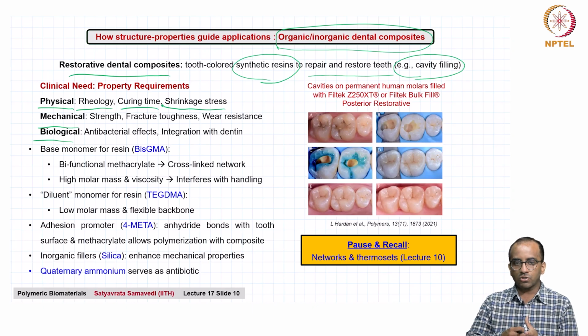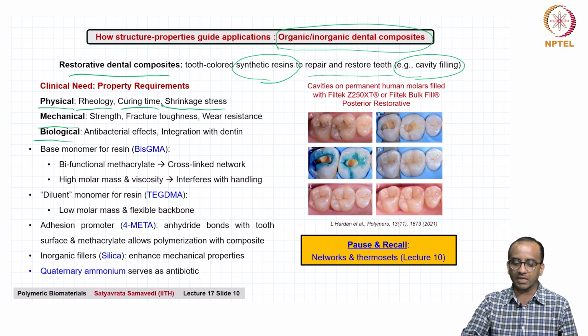And because they are in close contact with the teeth and enamel, they are constrained in that volume. So, they transfer that stress to the other side, and thus the interface between the resin and the tooth is subject to a lot of stress. Over time, that stress can lead to debonding, or small holes through which liquid can flow, food particles can get lodged, bacteria can get in, and the part can get infected. So, these are things that have to be taken care of very carefully.